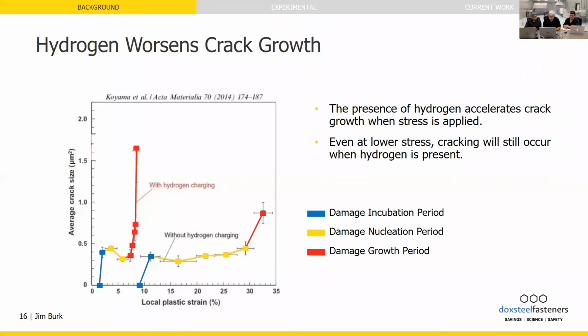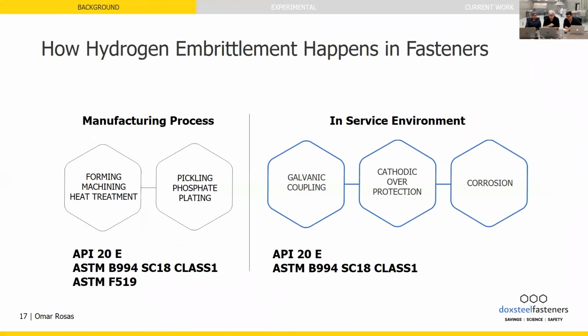Now, the material that doesn't have the hydrogen in it will achieve a much longer elongation. That means it'll get a third longer than it originally was before it will finally crack due to just normal plasticity. It's like saltwater taffy and glass. The brittle one is glass with the hydrogen, and the ductile one is the saltwater taffy. So I hope that's giving you a little bit of flavor for why hydrogen embrittlement is important, and also what it is. All right, thank you, Jim.